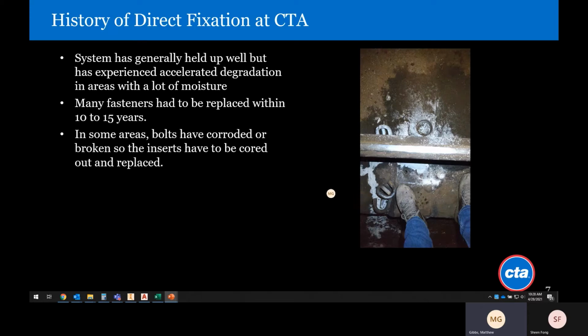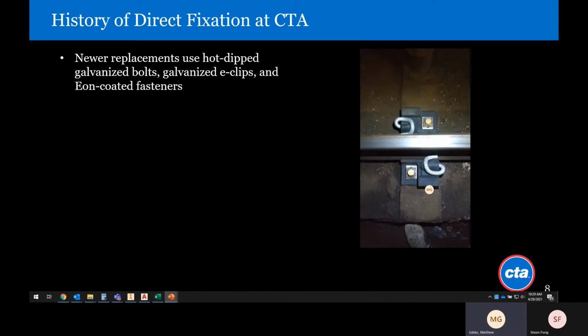And then even further, in some areas, the bolts have corroded or broken, and so the bolts can't be removed to change the fastener. And we've more recently been starting to core out and replace those inserts. So you can see here an existing insert, and then on this side, the insert's been cored out. Here's the replacement. So we're using galvanized clips, galvanized bolts, and EON-coated fastener for corrosion resistance. And hopefully this will give us more life.